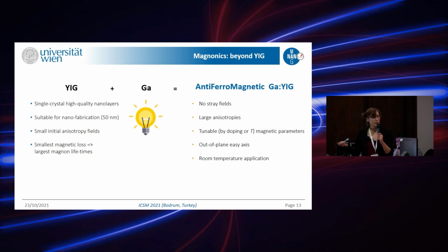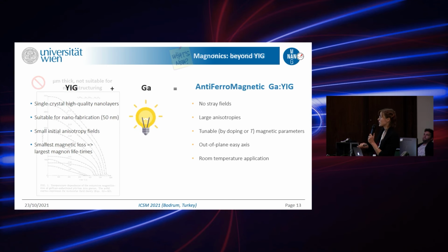But why would we like to do that? There is a lot of focus on this class of materials lately because they give you no stray fields. They have large anisotropies and can bring your original in-plane magnetization direction for YIG to out of plane, which will be preferable for practical application. And of course, room temperature application is also a key focus point in this research.